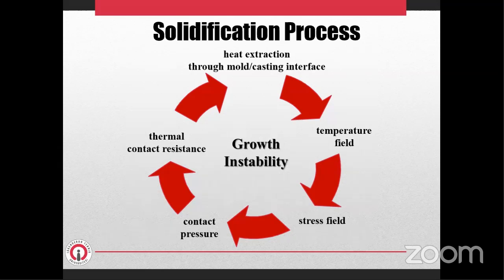These are the thermal contact resistances at the shell mold interface due to the surface roughness and other contaminant films. These thermal contact resistances change as a function of the contact pressure. Variation in thermal contact resistance affects the conducted heat flux along this region significantly. The temperature and stress fields in each solid layer are associated with non-uniform extraction. Variation in the heat flux leads to changes in the temperature and stress fields in the layers. These variations in the stress fields lead to thermal distortions in the layers, and the contact pressure at the interface between the layers changes.